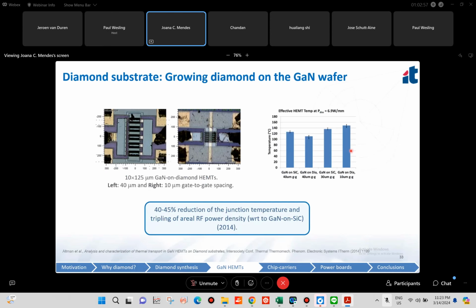And with this structure, they obtained what is currently the figure of merit of GaN on diamond. They obtained a 40 to 45% reduction of the junction temperature, and they managed to triple the areal RF power density with respect to GaN on silicon carbide in 2014. And now,